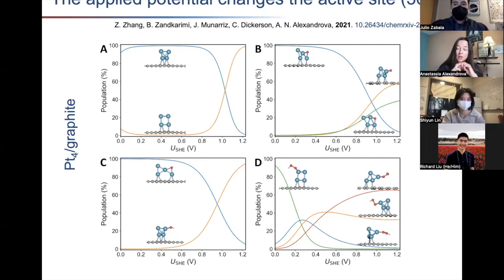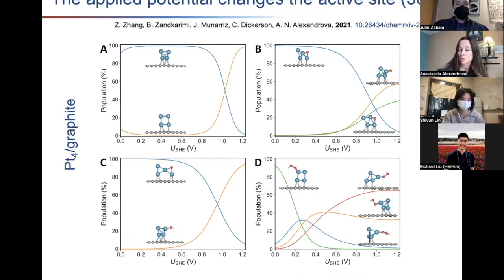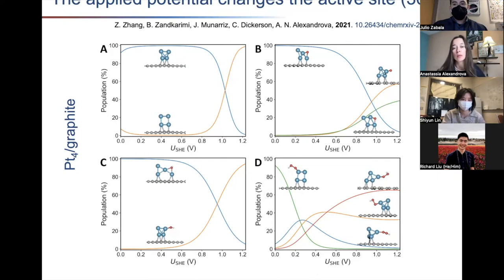The fact that size-specific activities are preserved in the experiment also tells us clusters are far enough apart to not sinter on the timescale of several TPD cycles we apply. But in practical catalysts put on a support in a messier way, of course there are native size distributions and clusters are prepared less precisely.